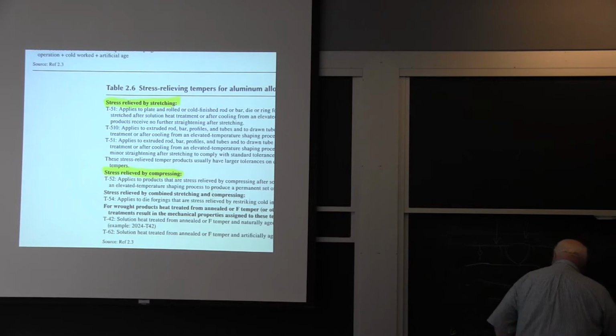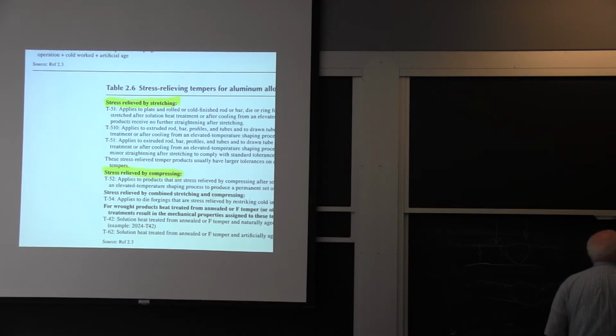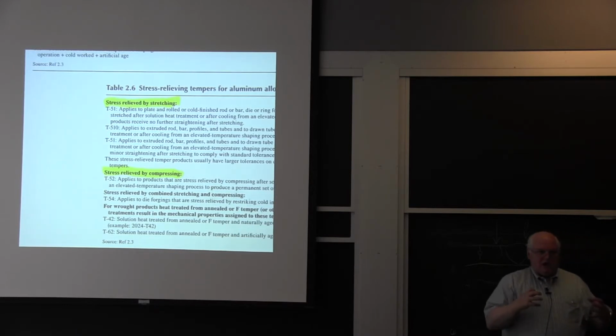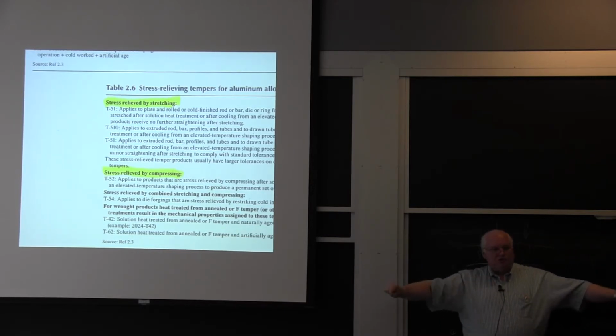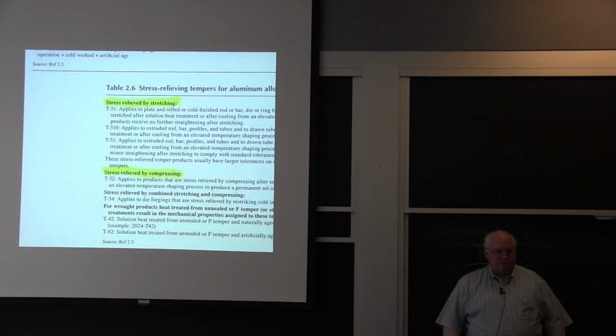T651. So it was a 6061 T6, which is the peak of the precipitation hardening curve, and the 51 on the end means they had stretched it. And so that 3.5 inch diameter bar had been put in a great big machine and stretched, and there are no residual stresses from the heat treatment, okay? Well then, when Sikorsky got it, they sliced it up like a bologna, and they machined the thing, and they reheat treated it. Well, when they reheat treated it, they wiped out the stretching that had relieved the residual stresses. They introduced new residual stresses on quenching, and they didn't do anything to relieve the residual stresses.